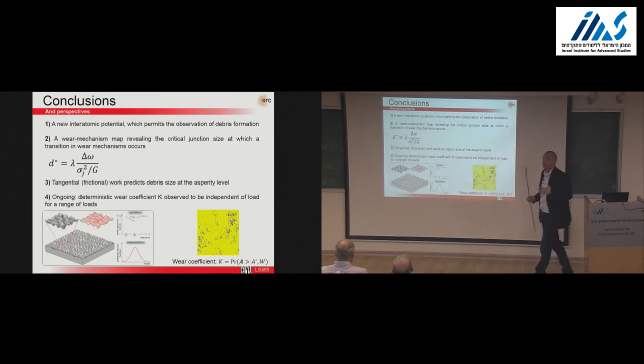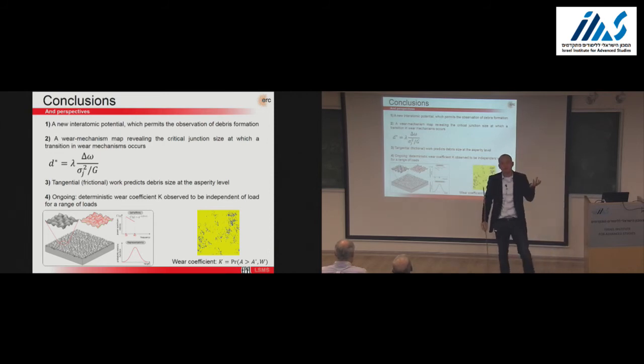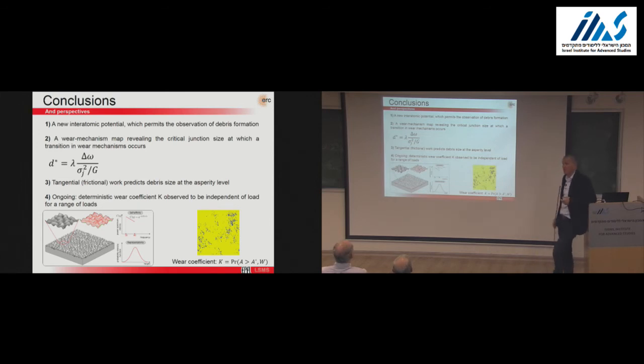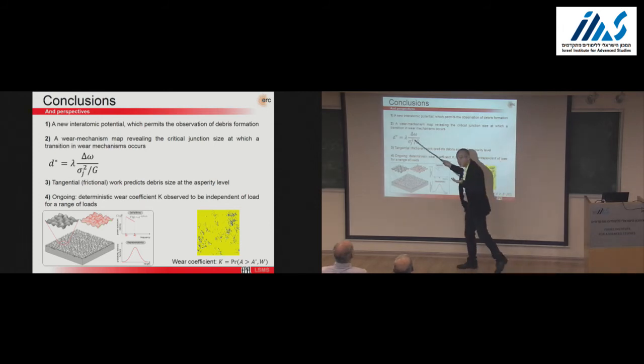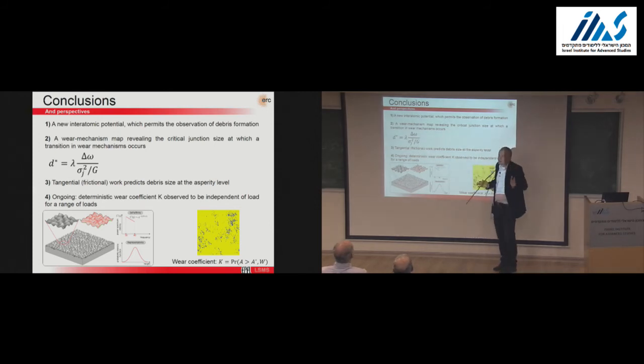So we have a new potential which permitted us to observe Archard debris formation mechanism to try to make baby steps in understanding of wear. We have this critical length scale that explains, in our opinion, the transition between what can be seen at a small scale and a collision between large asperities at the engineering scale. The tangential frictional work predicts the debris size at the asperity level. We need to include interactions between debris, which we do not have at this point.